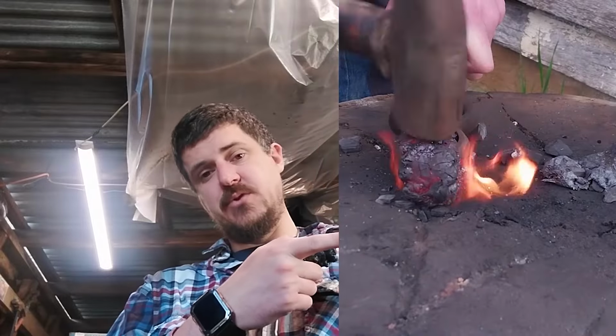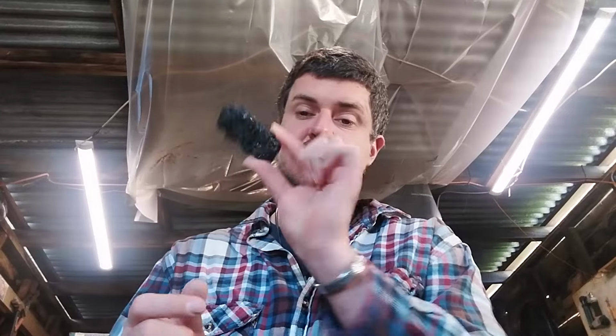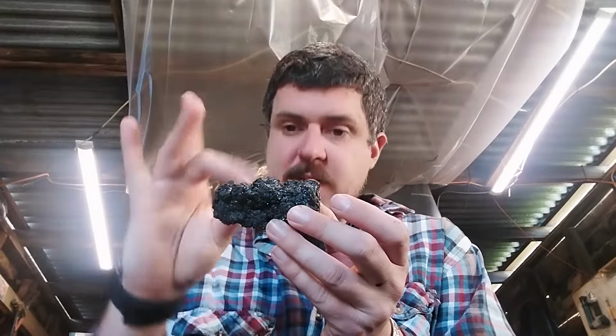I did a little bit of it when we tipped it out of the crucible, but my goal wasn't to try and really consolidate it there. It was just to get it into a workable mass so that I can just hold this in tongs and do this in the forge. So what we want to do is, at forge welding temperatures, with the aid of a bit of flux, squish this into itself until it won't squish no more. It's one of those things that you got to sort of play by feel. As we try and collapse it, some of it's going to forge weld shut, like those air bubbles in there. We need to try and work those voids out to the outsides, and press them shut.